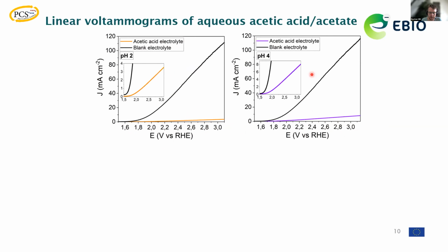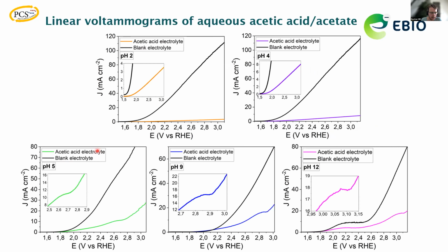So for us, that's the clear indication that there is no Kolbe oxidation yet occurring. And I will also confirm this in a moment. But before that, I like to point out that at higher pHs of pH 5, pH 9, and pH 12, we could definitely see this kind of plateau region that is indicating the transition between the oxygen evolution reaction occurring and the Kolbe processes. So the region of interest we are operating our experiments in is then, of course, in the potential range above 2.8 volts.